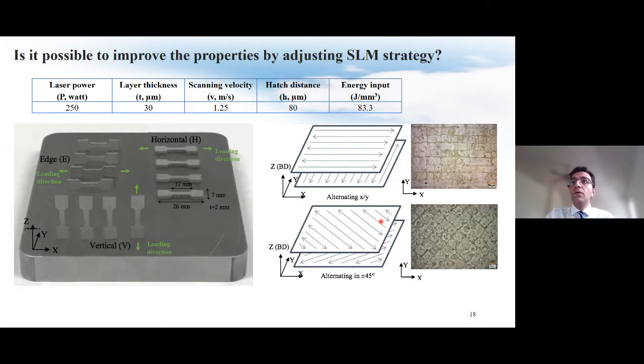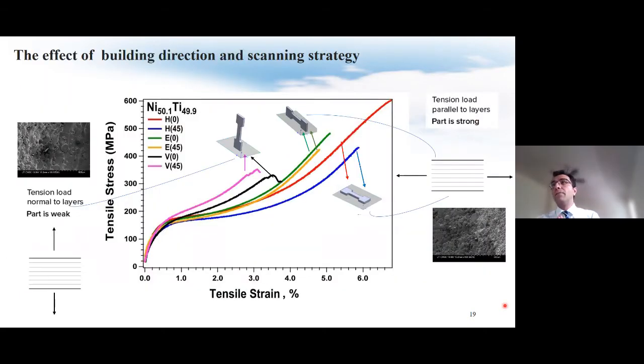As you can see here, we could change the orientation between each laser track and loading direction. Noteworthy, the newly optimized process parameters were used for the fabrication of these specimens. As can be seen in this slide, it was found that the part processed horizontally with a scan strategy of alternating 0-90 degree resulted in the highest mechanical strength.